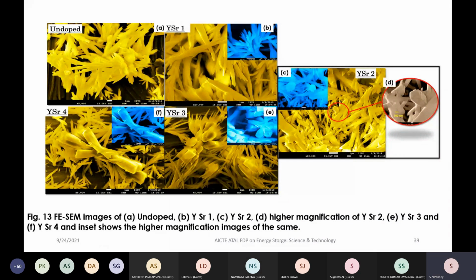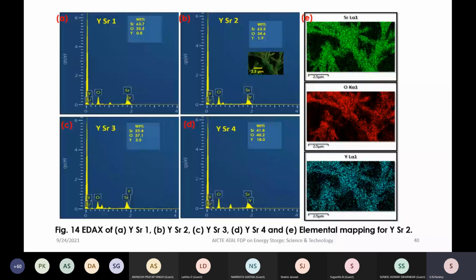The characterization that one can have is the EDX. So in the EDX also, yttrium is there, strontium is there, oxygen is there. So this confirms that the doping has taken place, and one can see the weight percentage of the different components that is given here. Strontium 63.5, and oxygen, and yttrium is here. And these pictures also show that whatever doping we have done, it is there. Strontium is also there. So it has confirmed, then one should go for the CV.